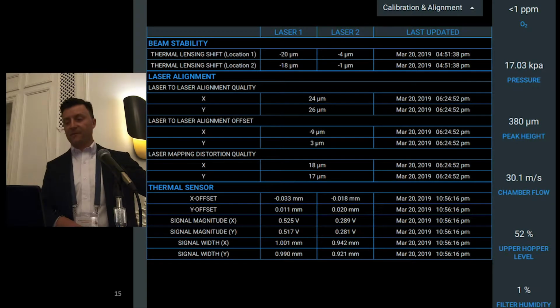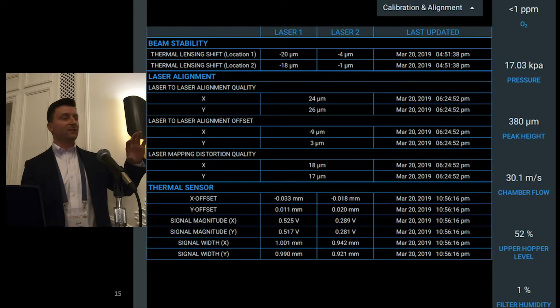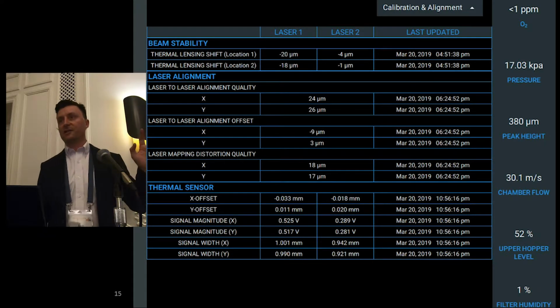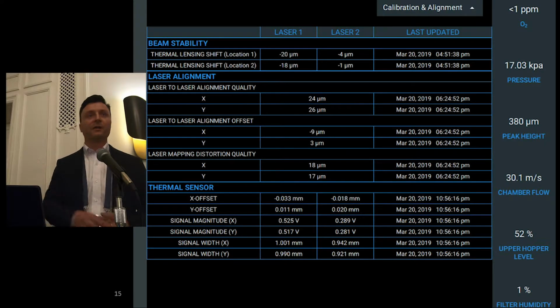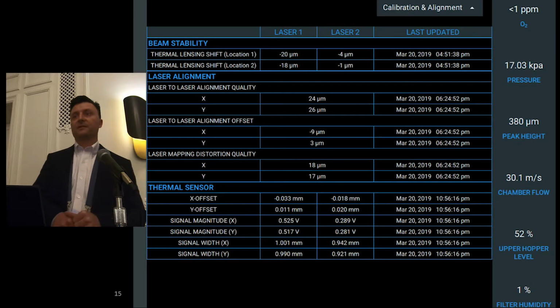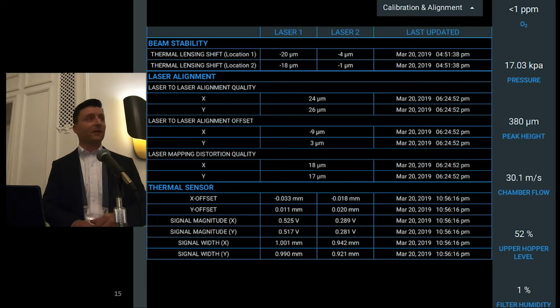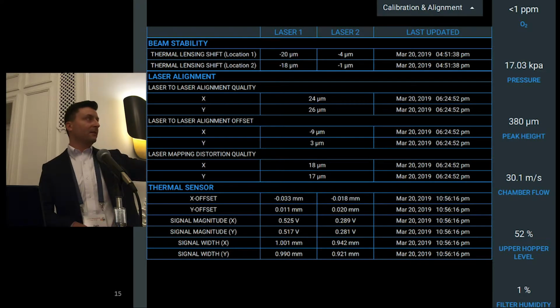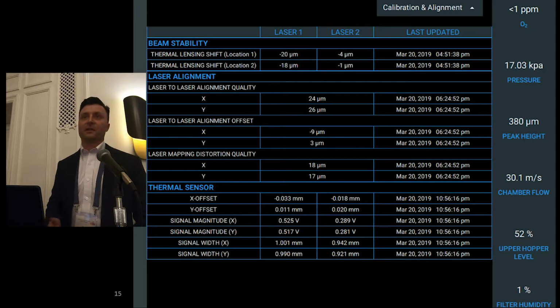Over on the left-hand side too, we have kind of our measurements that are of use, and these are always reported live. This is configurable, so you can change which sensors appear on the UI while the system's running. Generally, we're running at less than 1 ppm oxygen, which is pretty good. One of the reasons we're able to do that is that the people who designed our system are used to designing systems that are full of selenium and arsenic, and you want to keep those gases in and the other gases out. So they designed a very pressure-tight system where you can get to these very low oxygen levels and operate there. Another thing that we have here is humidity. That's something that is being talked about more and more, and it's something that should be tracked because it can be a root cause of failures.